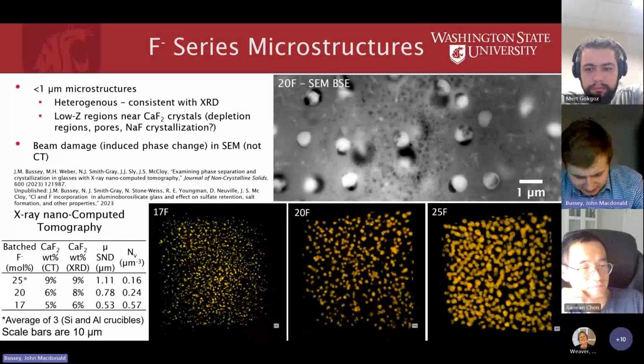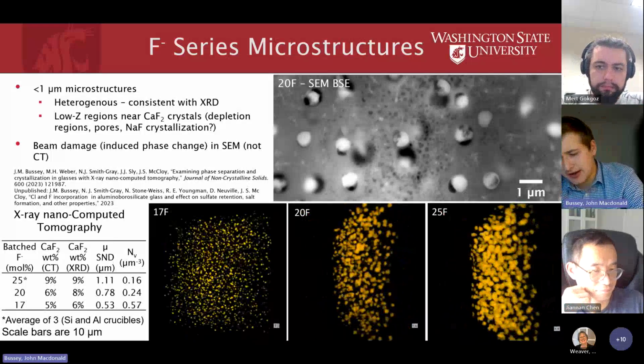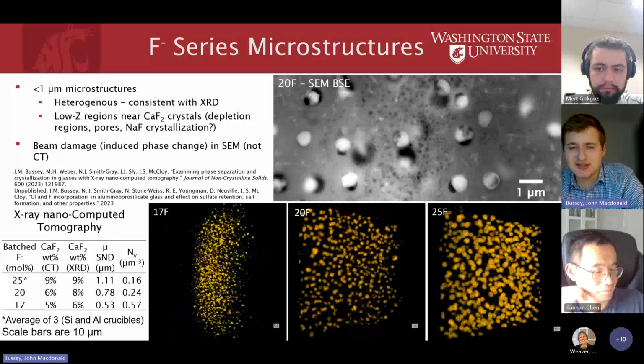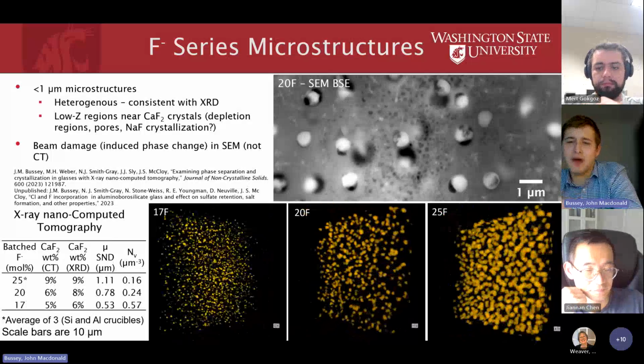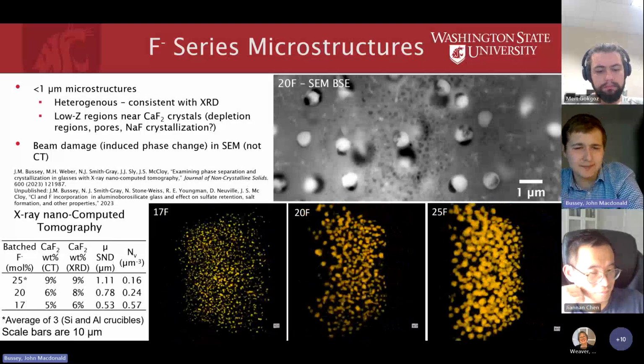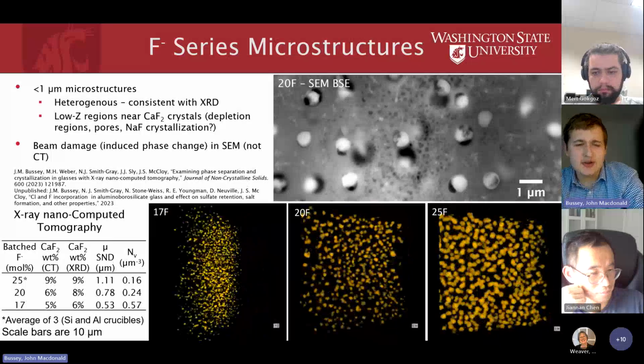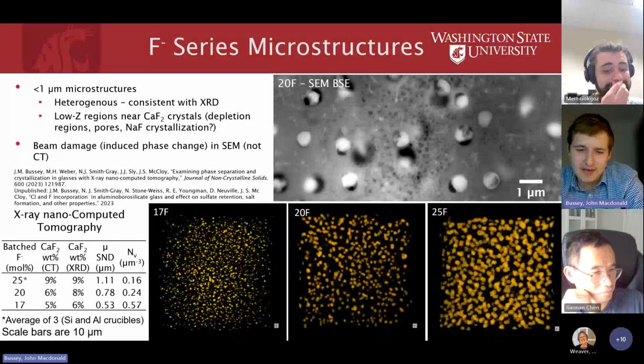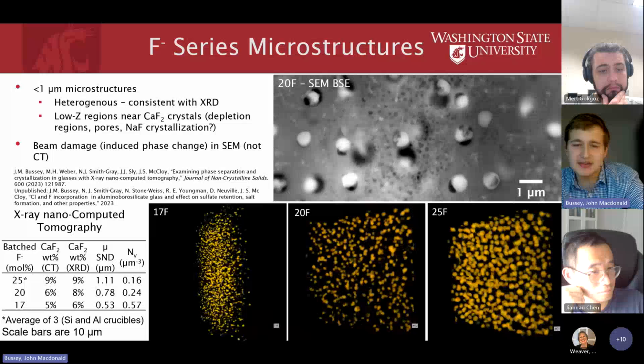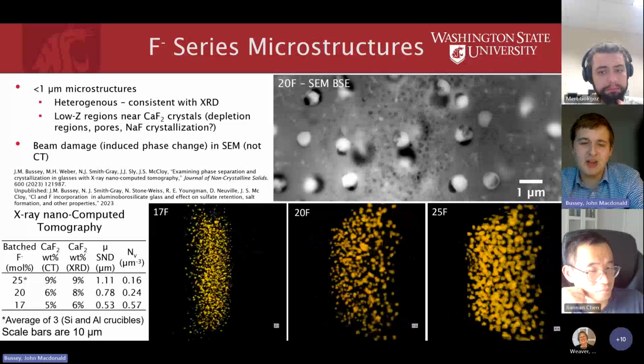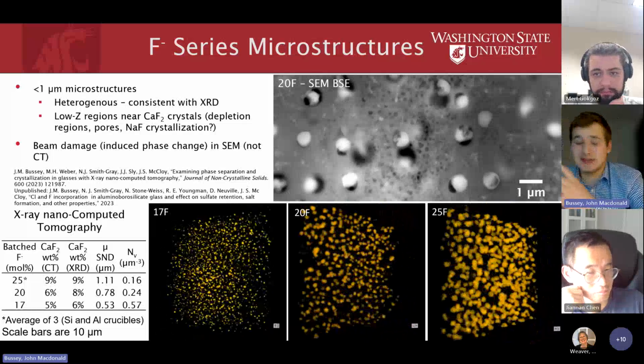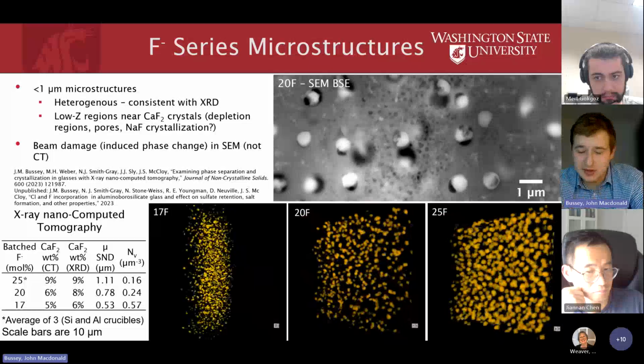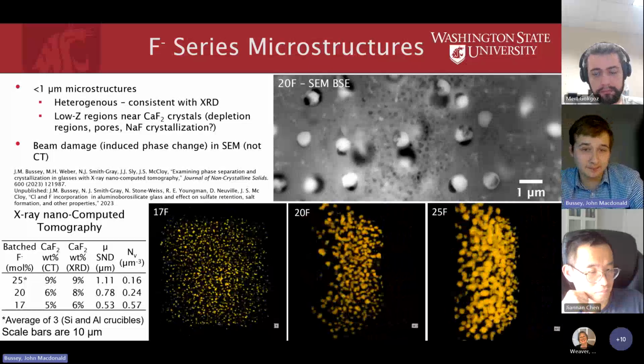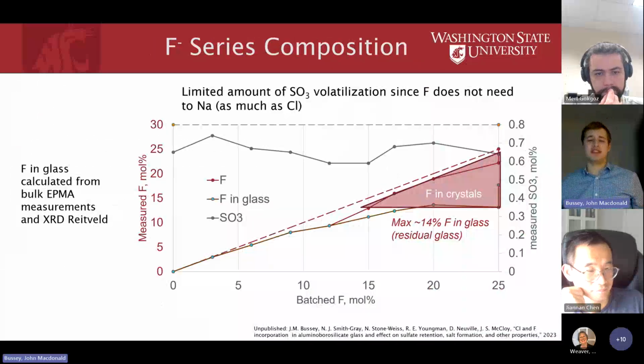And it turns out there's been some work out of Australia that has shown that calcium fluoride crystals are fairly durable and are probably okay to be in a waste matrix. The question of which crystals you can have, and whether you can have them, is certainly ongoing, but calcium fluoride appears to be, unlike something like nepheline or sulfate or a sodium salt, something that's more okay.